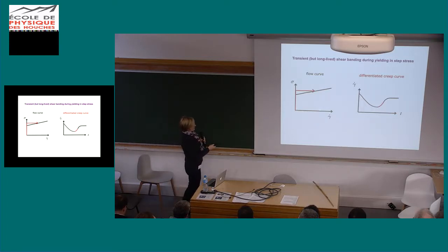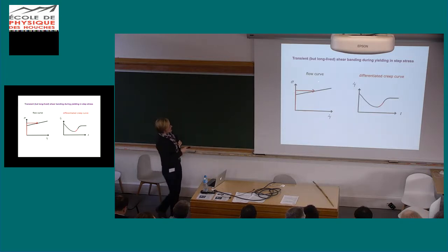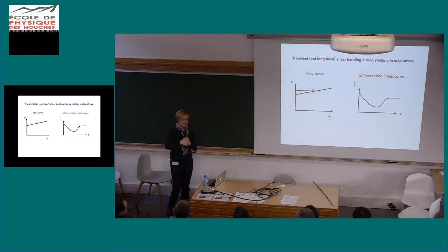Now, there's another common protocol that's done instead of shear startup, and that's to take a well-rested material, and instead of jumping the strain rate, you jump the stress to some constant value and then hold it fixed, and then you examine the way the material creeps. So you've applied a constant load, and you're asking how the strain evolves, how much the material creeps by. The creep curve is the strain as a function of time. Here I'm showing the time differentiated version, so the differentiated creep curve on a log-log axis.